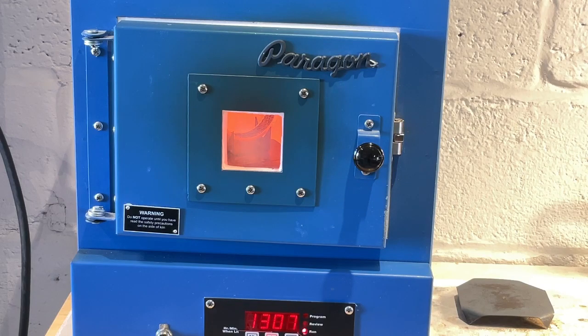But yeah, it's not going to be hard to tell because it's black enamel, but it looks really dark and crusty, and it has to completely burn away. And there's a lot of glue in there, so it's going to take a little extra time. And again, I'm not so worried, but when we get to the top, it's going to matter a lot that the glue is completely burnt away. So there we have it. Yeah, so a little extra time.